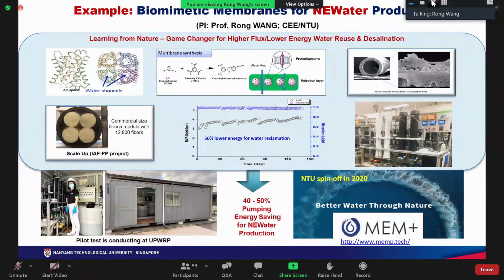We have scaled up the fabrication of the biomimetic membranes to an 8-inch size membrane module containing 12,800 pieces of the fibers. This is the hollow fiber RO type, and the membrane can operate at a low pressure for brackish water and NEWater application. Currently, we have a pilot system running at the Singapore local NEWater production plants, and the testing has been over 220 days. The capacity is 14 cubic meter per day for clean water production.